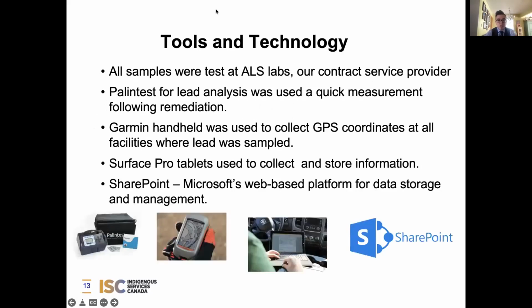Some of the tools and technology that we use. We sent all our samples through the ALS laboratory. That's our contracted service provider. We also utilized a product from Palintest that provided on-site testing for lead analysis. This was done supplementary to the use of the lab. It was able to provide immediate on-site results based on remediation that had been done, whether it was changing a pipe or changing a fixture. And we also sent a set of samples to the lab to verify our findings as well. Staff all GPS'd the sampling sites. We collected our information on our Surface Pro tablets, and information was collated, compiled and stored on our SharePoint.